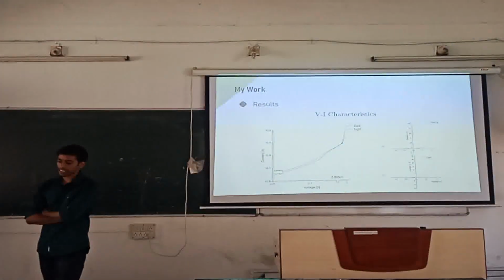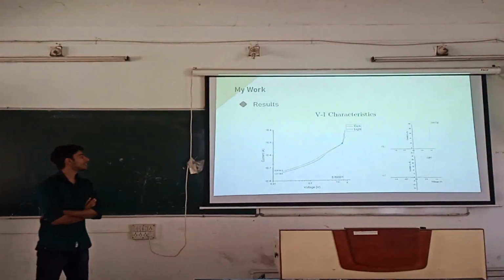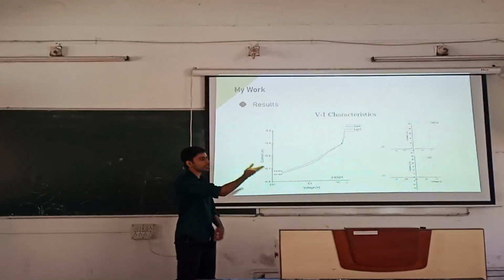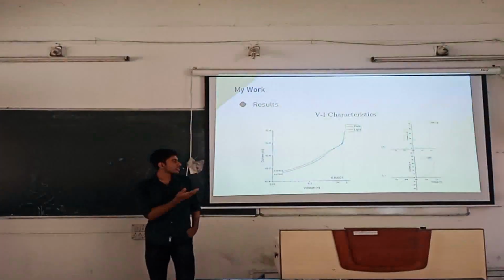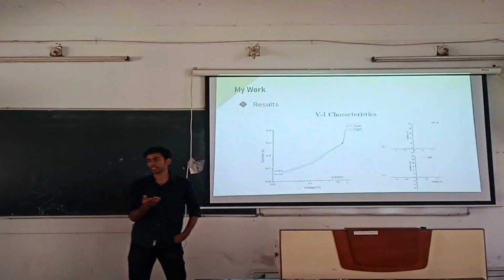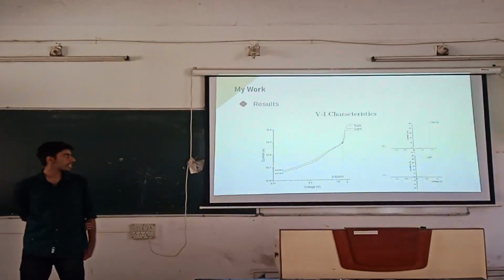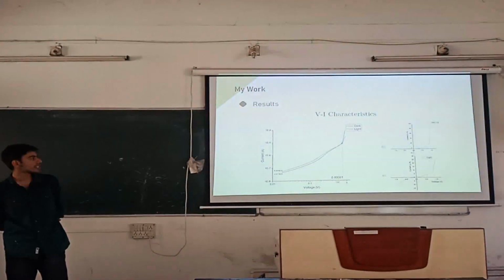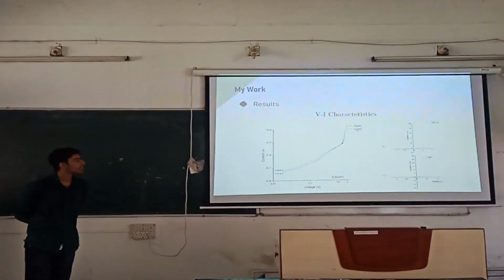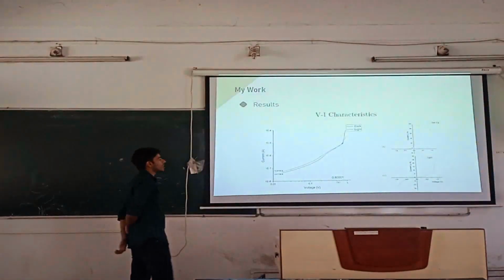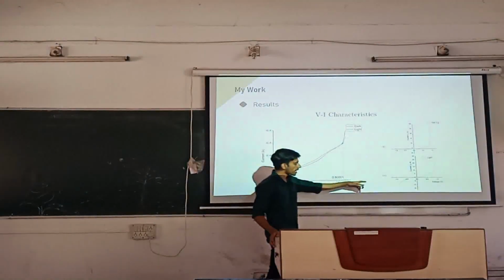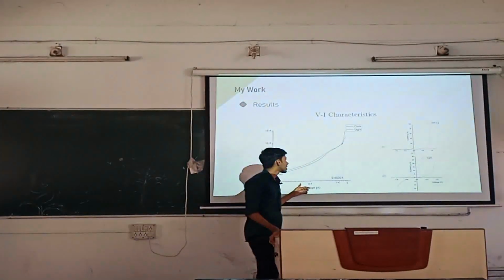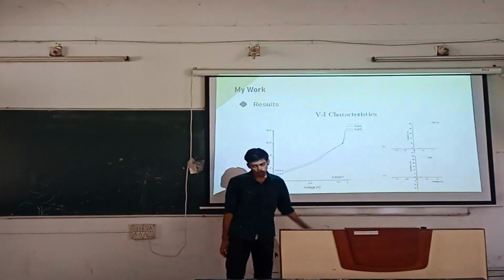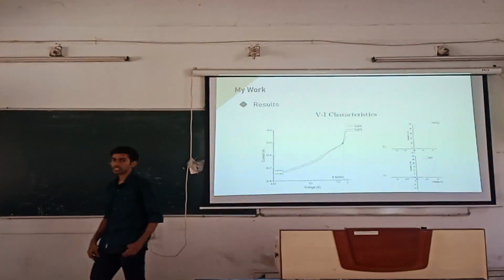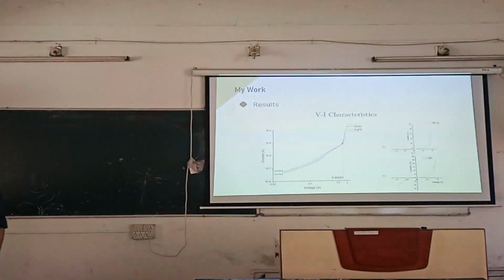After designing the tapping mechanism, we checked the VI characteristics. See, the VI characteristics does resemble that of a diode. This shows that it was a success, a Schottky diode has been formed between copper and zinc oxide. We were seeing a knee voltage. This is the actual plot, this is a log plot, and at 0.8 volts there was a barrier potential. So the growth was successful.